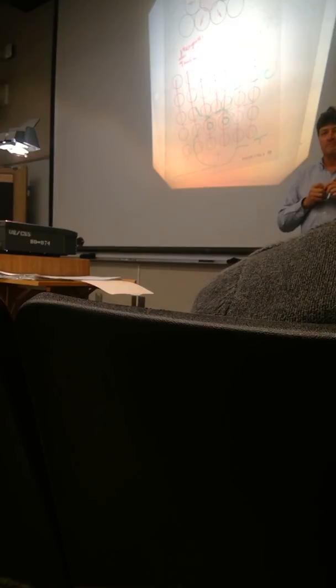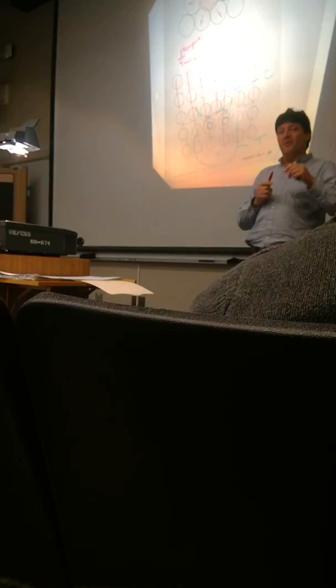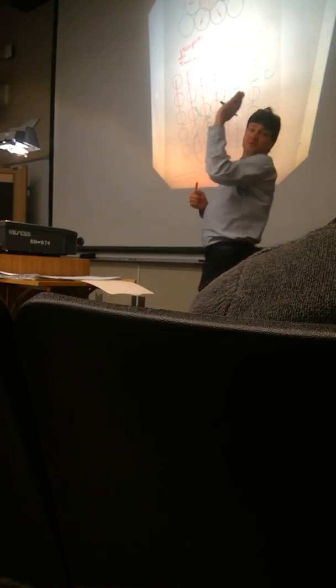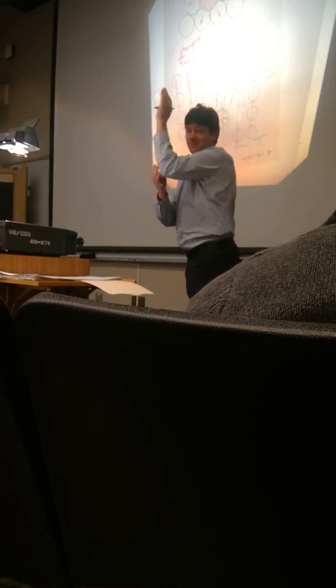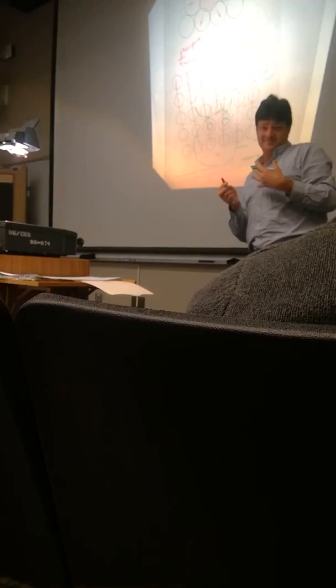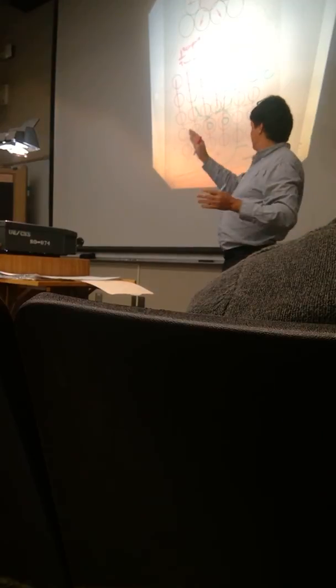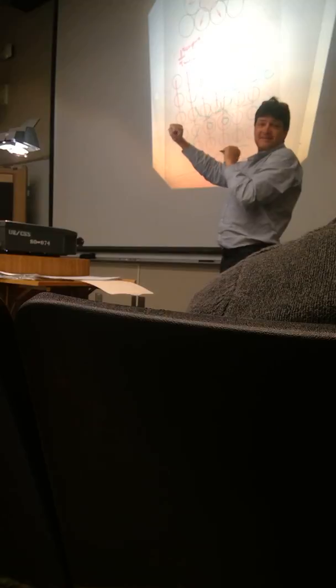Are you saying that an impurity will actually diffuse to the end of a dislocation? It can. Okay. Or dislocations move and hit and stick. Okay. So it can happen both ways. And there's what's called strain aging. So if you have dislocations that are stuck, you then apply a force and you break them free. Okay, then you stop your test and you know what stress that was moving at.